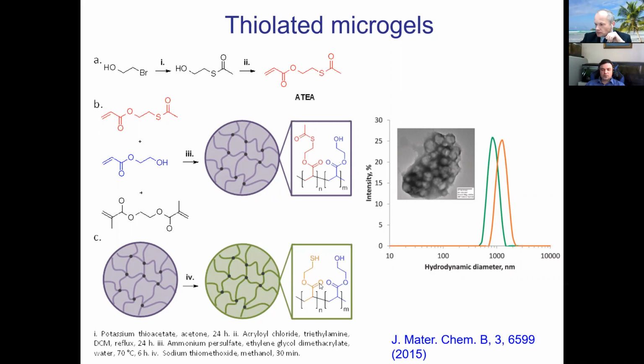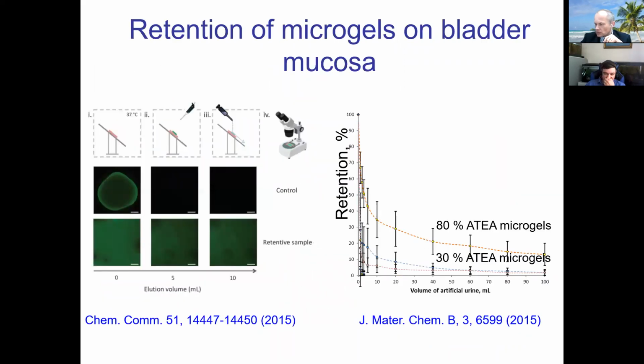So of course, we have done all the extensive characterization of the systems, and we also demonstrated that the systems adhere to mucosal tissues. How we test adhesiveness? We have developed several methods of our own and also used well-known literature methods. One of the methods is called flow-through fluorescent assay. When we use a piece of mucosal tissue, typically taken from an animal, for example, it could be bovine eye, we put it on a slide and we put our mucoadhesive formulation loaded with fluorescent dye, and then we wash it off with the artificial body fluid.